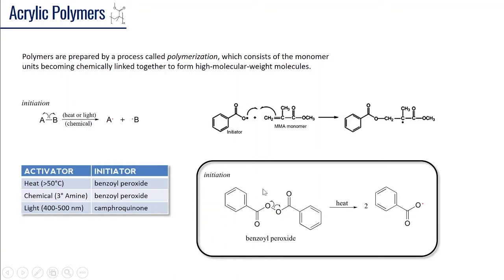The advantage of having a heat-activated acrylic is that we can drive the reaction to completion. In the case of a denture, we'll stick that denture into a bath of hot water to allow for this reaction to take place.